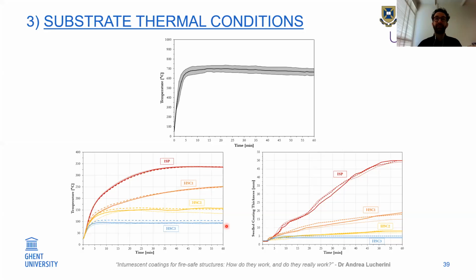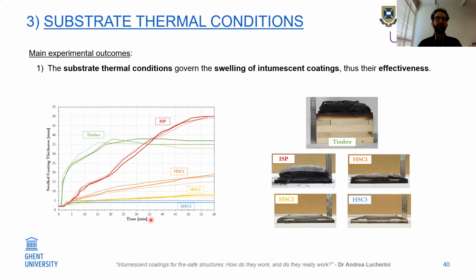What is interesting is that in terms of the swell coating thickness, you can see that the coating swelled in completely different ways based on the different thermal boundary conditions at the substrate, or at the exposed surface of my steel plate. In terms of experimental outcomes, I showed that the substrate thermal conditions again govern the swelling of the intumescent coating, and therefore its effectiveness. This is the comparison between the 3 heat sink cases, the insulated case and the timber case. And here you can see the different coating swelling at the end of the experiments.